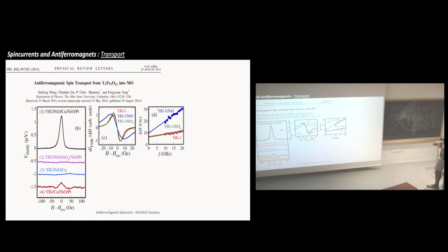The second one, which is very nice, which has been done at the same time, they are doing exactly the same, except in addition they have checked the dependence on frequency. With the dependence on frequency, you can just look at the line width of the ferromagnetic resonance, and you can see that in case of NiO you have a huge increase of the slope. This is an increase of the Gilbert damping, which I already mentioned at the very beginning. And this increase of the Gilbert damping is a proof of an additional channel to carry away the angular magnetic momentum, so in other words, carrying away some spin current.